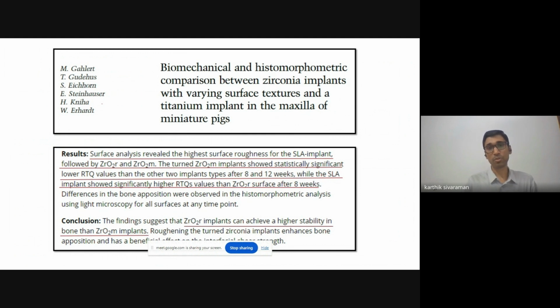On initial examination, it was found that the SLA titanium surface had a rougher surface, and the pigs were then subjected to extraction of teeth in the maxilla, two teeth in fact, and these were replaced with these sets of implants, with the titanium SLA serving as a reference. Just a minor correction: initially, the extractions were done, a healing period was allowed, and then the implants were placed. So we had a healing period of around 4 and 8 weeks, subsequent to which a reverse torque test was done and the values compared. A set of samples were also taken for histomorphometric comparison between zirconia implants and the titanium SLA surface.